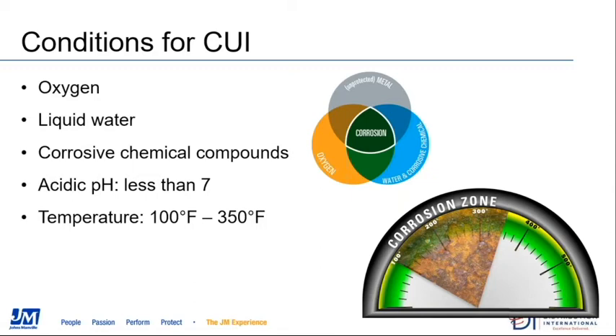When you're looking specifically at corrosion under insulation, the insulation material itself has unfortunately historically had a reputation of possibly causing corrosion under insulation, but the insulation material itself cannot actually cause corrosion. It's usually caused by the ingress of water, as we've discussed. However, the presence of insulation can promote corrosion by either retaining that moisture and or the contaminants that enter into the system from the environment, or possibly by the occurrence of electrolytes within the insulation material leaching to the pipe or equipment surface, and therefore increasing the corrosive nature at that interface.